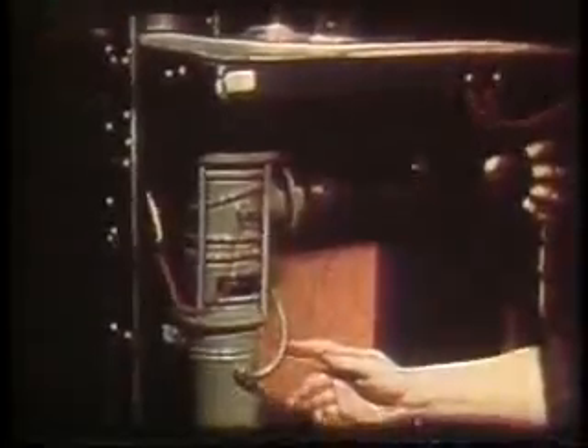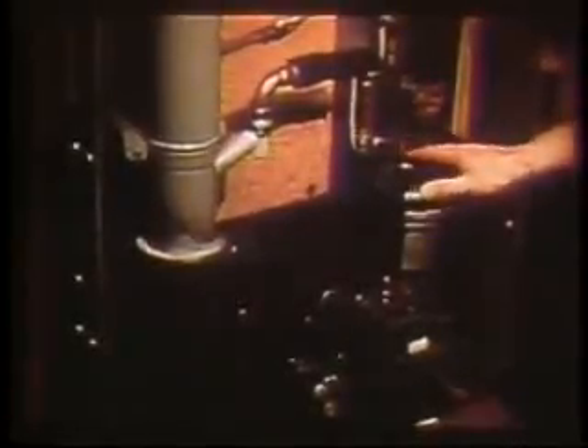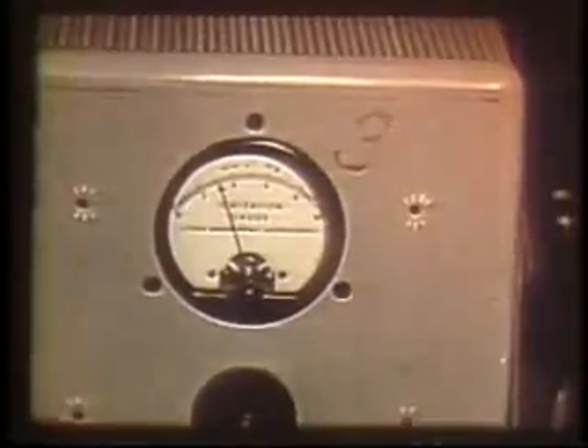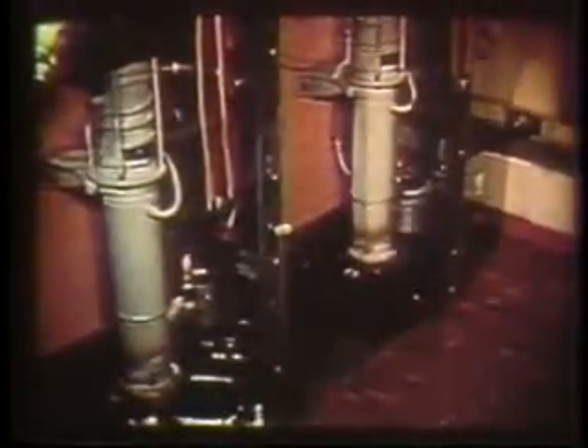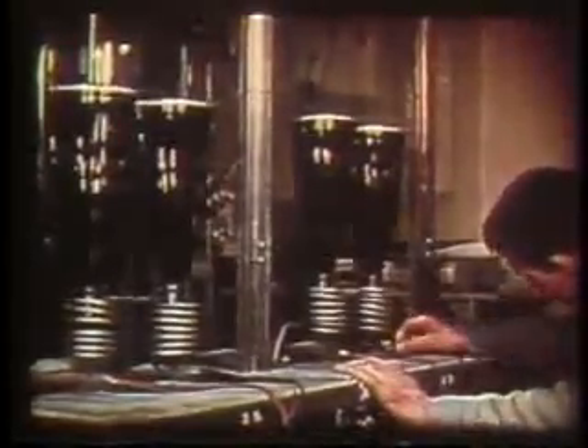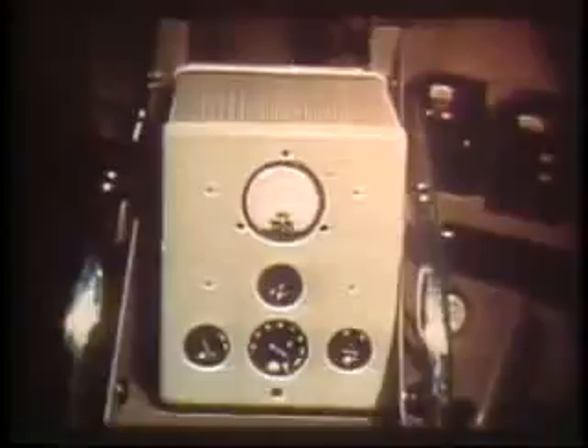Each of the pump stations consists of an exhaust manifold, a water-cooled charcoal trap, an oil diffusion pump, backed up by a mechanical pump. Careful attention and extended pumping time permit an ultimate vacuum close to 1 times 10 to the minus 7th millimeters of mercury to be reached, even before the getter is fired. This high vacuum does much to extend the expected tube life. Almost all early failures of cathode ray tubes are due to gas molecules in the tube forming positive ions when they are struck by the electron beam, and these ions soon destroy the cathode material.